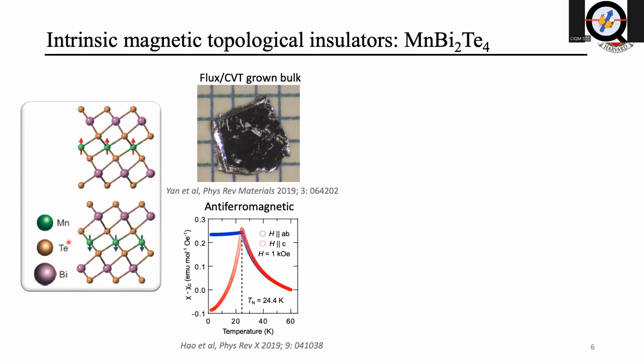So because the manganese atoms here form a well-ordered lattice, they reduce the disorder effect contributed by the random dopant in the extrinsic magnetic topological insulator. And as a result, it may increase the quantum anomalous Hall effect operating temperature. So the MBT can be grown either by the flux method or the chemical vapor transport method.